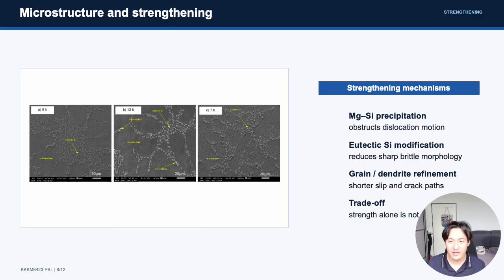The SEM evidence shows that the heat treatment changes the microstructure. The T6 fragments and spheroidizes the eutectic silicon, and aging forms fine precipitates in the aluminum matrix. These precipitates hinder dislocation motion, so the strength and the hardness increase. However, strengthening is not the same as reliability. If a large pore or bifilm remains, failure may still start there. So microstructure improvements must be interpreted together with the defect condition.